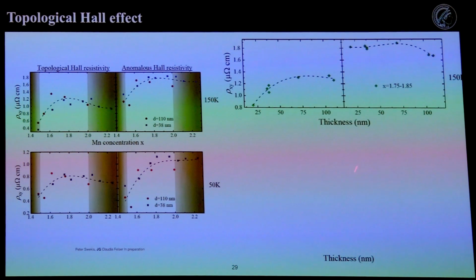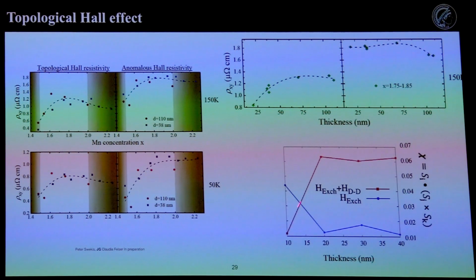Topological Hall effect things, so then the student went through and did a lot of work, so he grew this, and this is not even all the work I think he did. He's got about 10 times more data points. But he grew many different thicknesses and many different concentrations just to see how the anomalous Hall effect and the topological Hall effect behave. And this was the case of thickness, which I tried to reproduce. And so what we saw was that once you add the dipole-dipole term, it actually does curve off because of this anisotropy the dipole-dipole term gives to the system. I think this is the end.